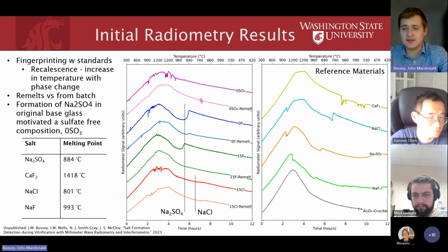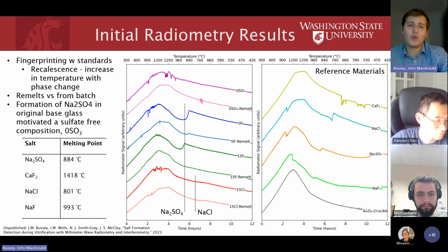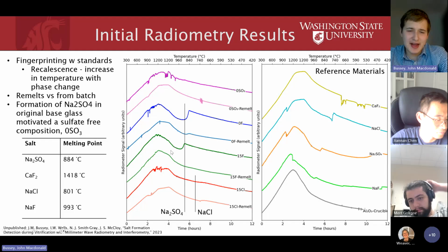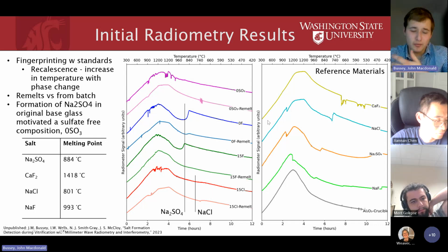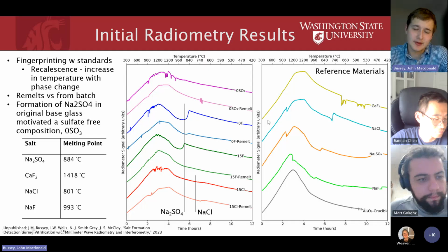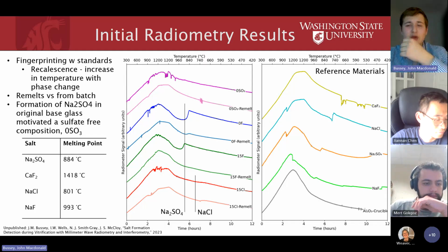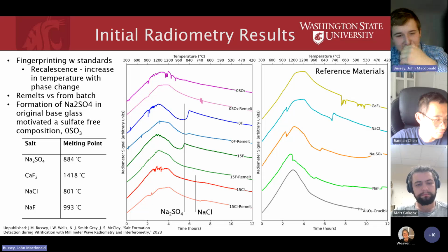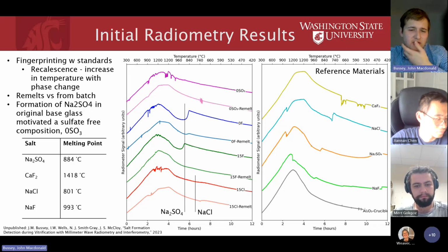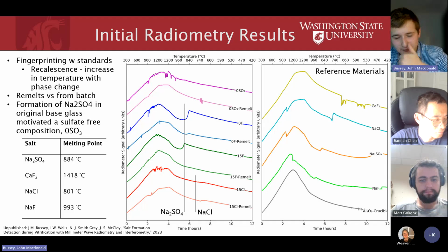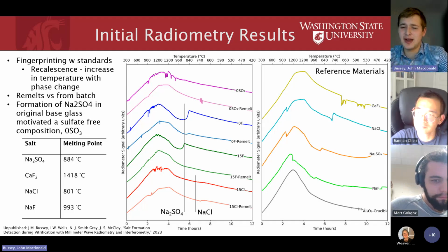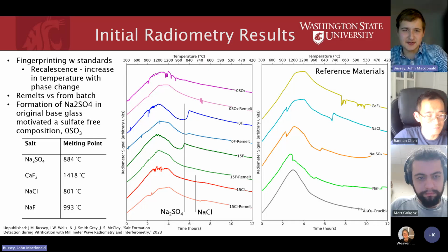A couple other things to note: we melted the glasses directly from powder, like we do at Hanford, the waste treatment plant, and then also melted them once they were all off-gassed with just the melt, and saw similar agreement, but without this feature here on heating, those ripples, and we are fairly confident they correspond to off-gassing. Some other things we observe is that even when we would expect the temperature profile to be flat, a significant increase is typically corresponding to salt formation. So we're able to see when there's salt forming and do some kind of fingerprinting with these standards we made.